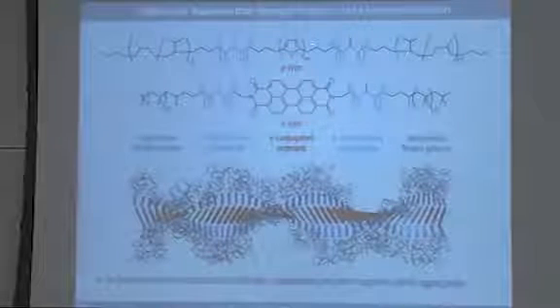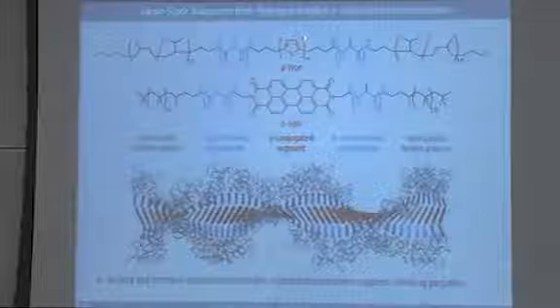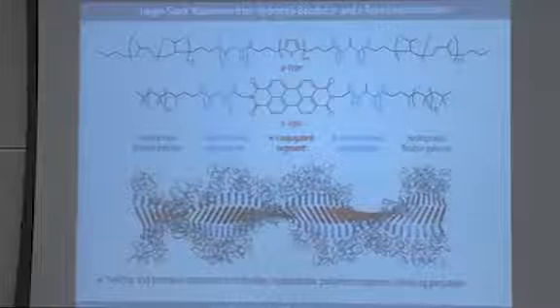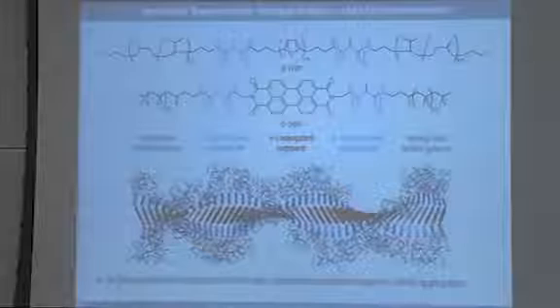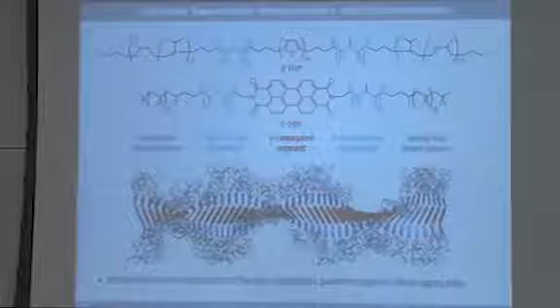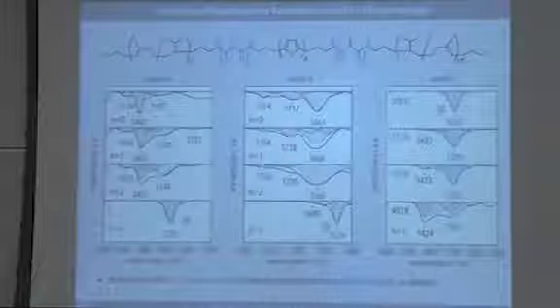And so after we had the molecules in hand, and after we had a tool chest of molecules that we thought would be appropriate for self-assembly, we investigated the formation of nanofibrils in solution. So the idea, just to repeat, is that we would like to take these molecules and dissolve them in an appropriate solvent, a moderately polar organic solvent to promote strong hydrogen bonding. And the molecules would ideally line up as schematically shown here, with the aggregation strongly promoted by hydrogen bonding between the peptides, but at the same time the helical twisting laterally limiting the aggregation so that we don't see bundles. And from a variety of different characterization techniques that, again, time does not allow me to go into in detail, but I'll be very happy to answer questions about it.